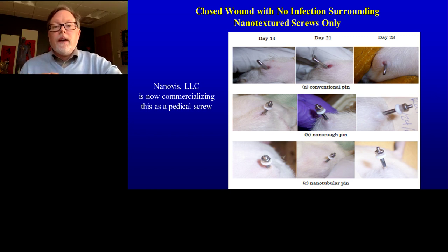So again, no antibiotics were used. This is simply putting nanotexturing on these devices, which helped reduce bacteria growth, allowed for skin to grow, allowed for bone to grow, and allowed for a successful material. So this one is also approved by the FDA. The silicon nitride example, I did not mention this at the time, but that has also been approved, the nanotextured version, by the FDA for orthopedic applications. So here's two examples of nanotexturing that has reduced infection and has been approved by the FDA for implantation.